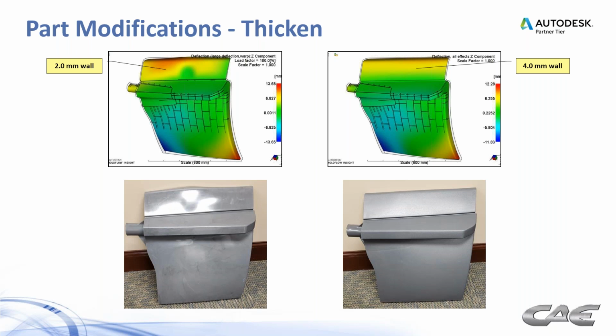Well, we tried stiffening it up by other features. We added ribbing, we did a bunch of different ribbing patterns and so forth. But ultimately, it took thickening that wall to fix the problem. They didn't want this big dimple in the middle of their part. And it's amazing how the simulation was able to convince people to make a solution that worked.